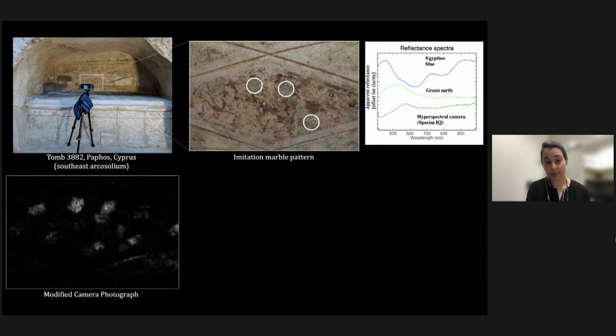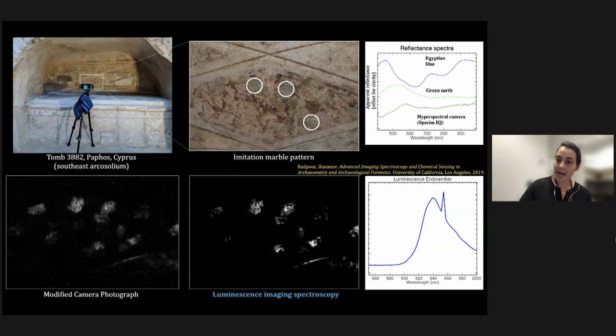Again, just for comparison, this was the modified camera photograph that we took. But using a hyperspectral camera and recording the luminescence data and doing statistical analysis to extract potentially a luminescence signature, I record this emission profile, I extract it and I map it, and I get this really beautiful image about where Egyptian blue is located in that painting.